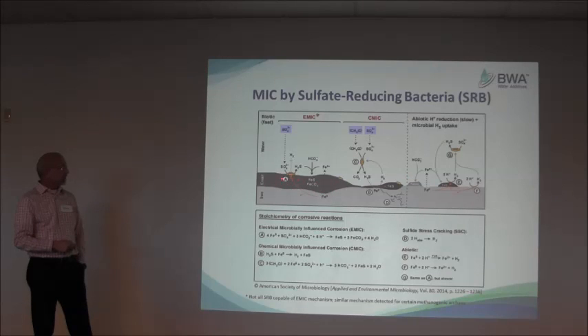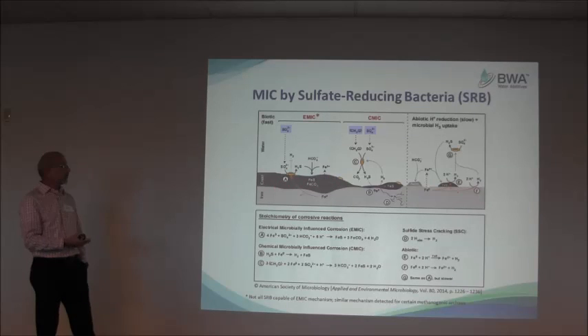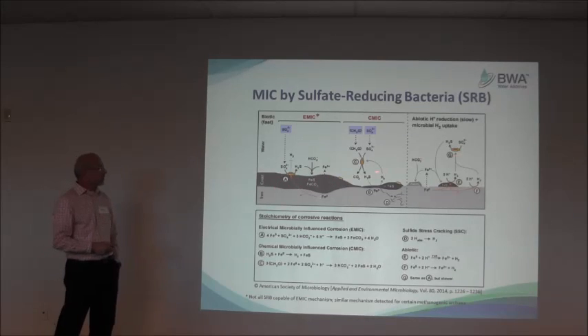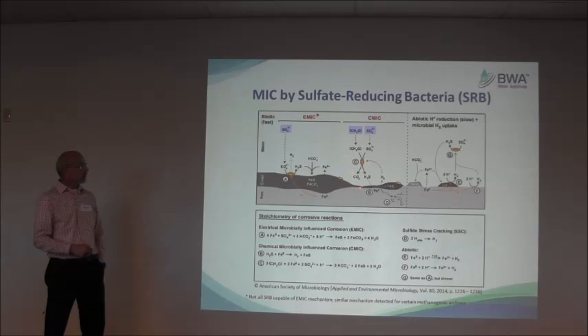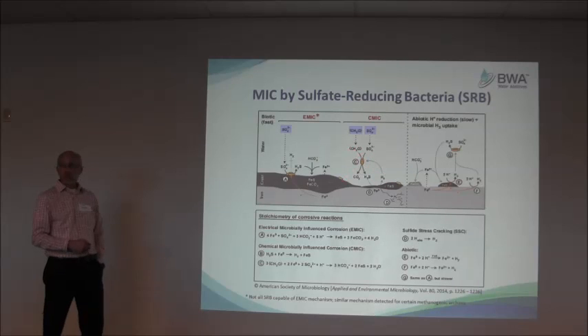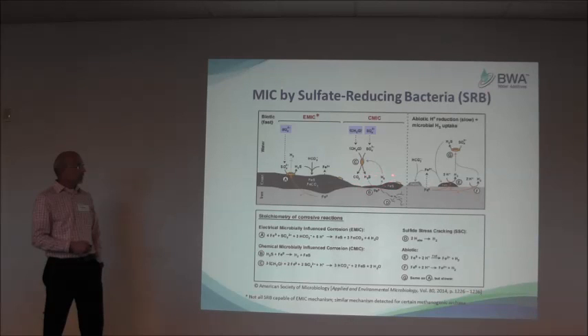Again, you can see you have to have organisms in contact with the surface — biofilm — for this to occur. There's another mechanism, more of a chemical mechanism, where they use hydrogen from the surface to reduce organics. They make H₂S, and it's the hydrogen sulfide that stimulates the corrosion process.